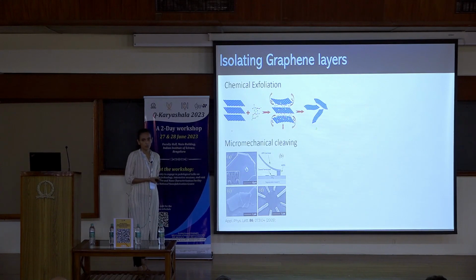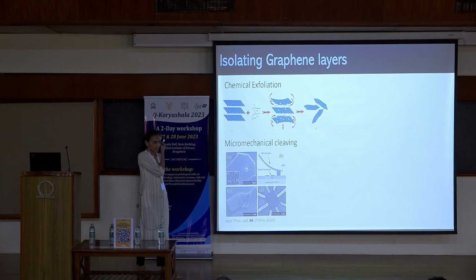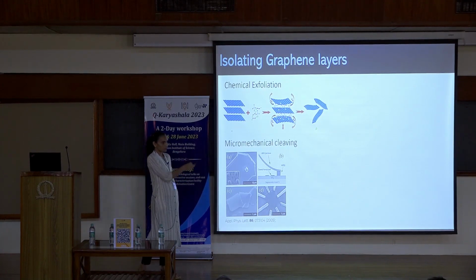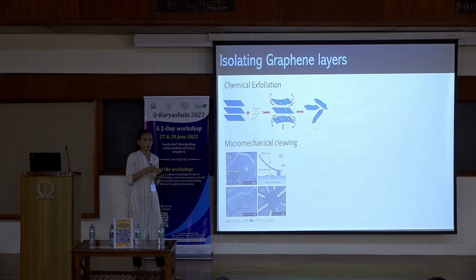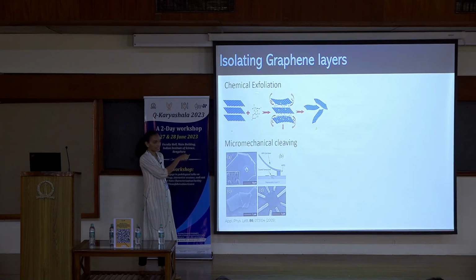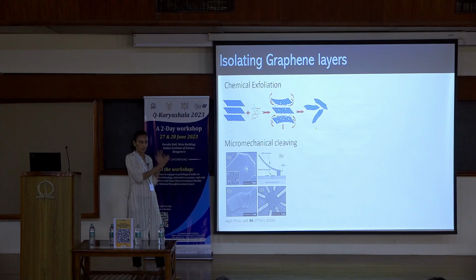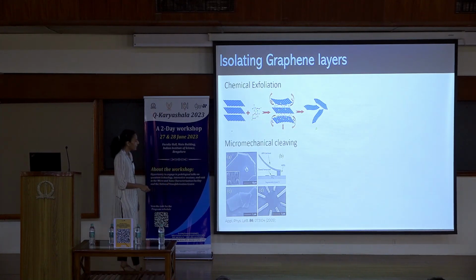So now let's talk about how to make this material, right? So the easiest thing that one can do is to take this material and sort of shake it, put it in a solution and chemically exfoliate it. So bring in some atom in between, so it's like forcefully getting these layers out, right? So that's one way of doing it, which is called chemical exfoliation. So you go from graphite to graphene by forcefully taking out these layers and separating them.